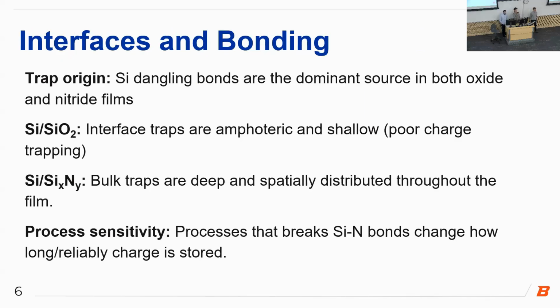So to quickly talk about the physics behind charge trapping, silicon dangling bonds are the primary source for both oxide and nitride films. In silicon dioxide interfaces, the traps are amphoteric and shallow, meaning only a little bit of voltage is required to get charges in and out, making them not very reliable for trapping these charges. In the nitride, the traps are in the bulk material. They're deep and spatially distributed throughout the film, requiring a lot more energy to get charge in and out. And so any process that breaks these bonds changes how long and reliably charge is stored.